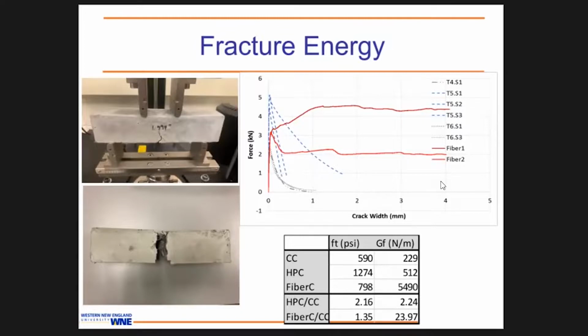Also in the bottom left corner, you can see the effect of the orientation of the fibers. You cannot control the orientation of the fibers. That's what you're going to get. That's why after the peak you have such different post-peak behavior between the two samples. As much as we would like to have well-distributed fiber orientations, that is practically impossible, so the total energy will vary much. But now we are in the phase of testing the high-performance concrete with fibers for fracture energy.